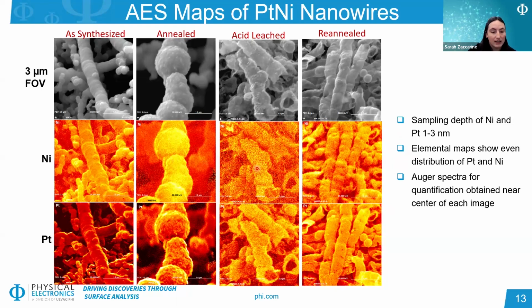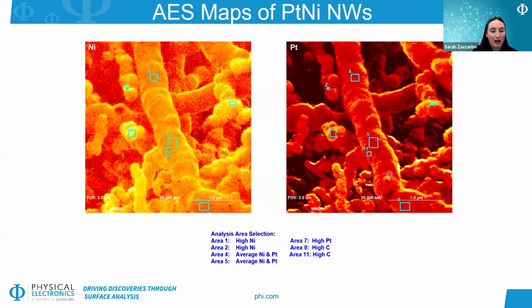We see a slight difference in signal amounts with these different treatment steps, and once they're acid leached particularly, these maps look a little bit different compared to the other ones. Generally, the platinum looks a little bit lower intensity, which you would expect since that's very thin at the surface. And then after this reannealing step, we see some changes overall, but generally they look fairly uniform, but because we have the small beam size with this technique, we wanted to analyze this a little bit further, more quantitatively, and see how uniform that chemistry really was.